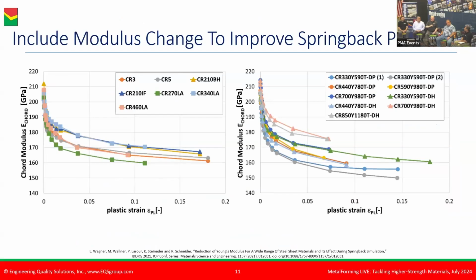There is one way to cut out a lot of the trial and error that Art referred to, and that's use metal forming simulation. When it comes to necking failure, most metal forming simulation software with the right inputs are really accurate to predict those, so you can actually do your trial and error on the computer. But where the challenge is on higher strength materials is the dimensional accuracy. For many years, that has been one of the downsides or challenges with metal forming simulation. But that's even gotten to the point where simulation can fairly accurately predict your dimensional concerns, but you need to capture Young's modulus accurately.